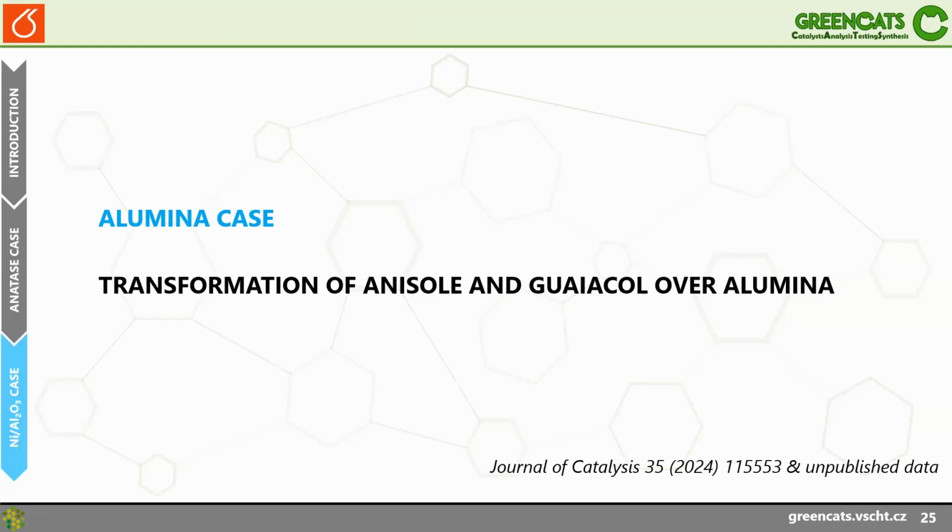I will not be exploring many types of alumina, just one, but we will be looking specifically at anisole and its conversion over nickel and copper modified alumina, to show that there are sites in alumina that are intrinsically active in the reaction, and that copper in this case especially helps to improve the stability of alumina alone, which otherwise deactivates quite quickly when reacted with anisole.